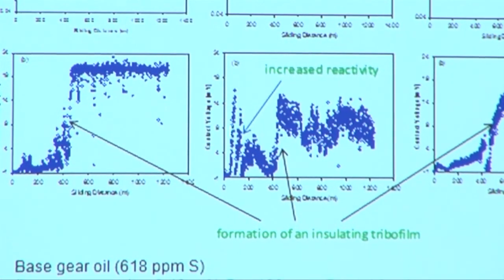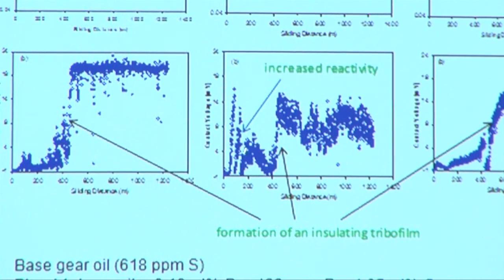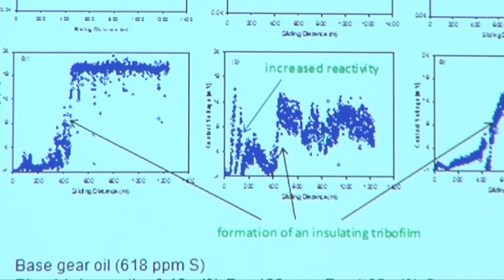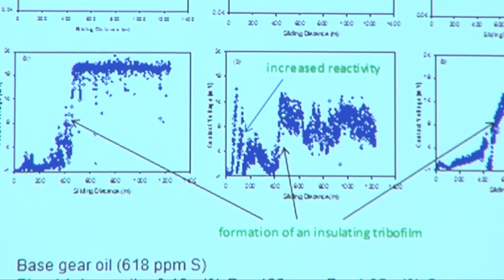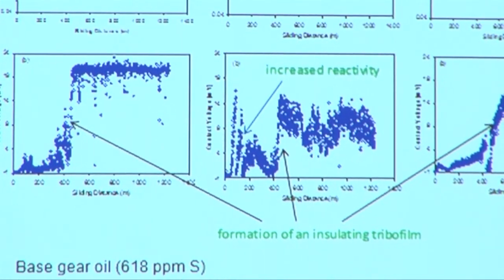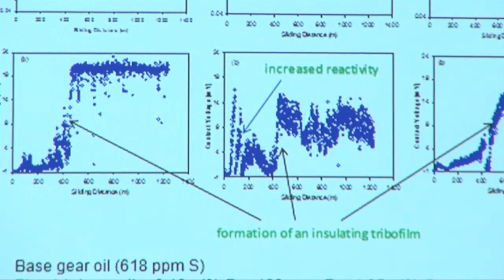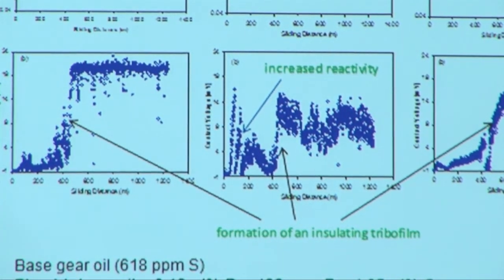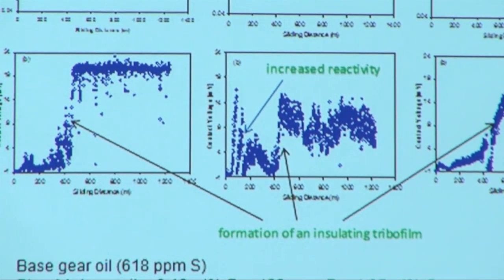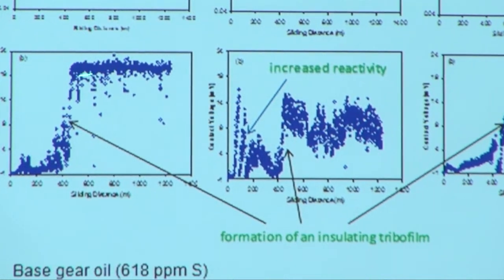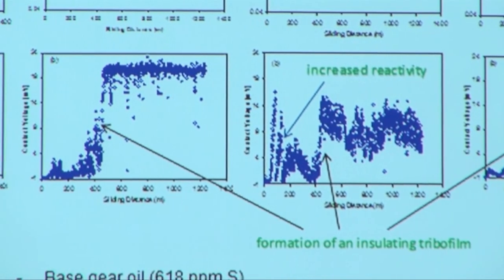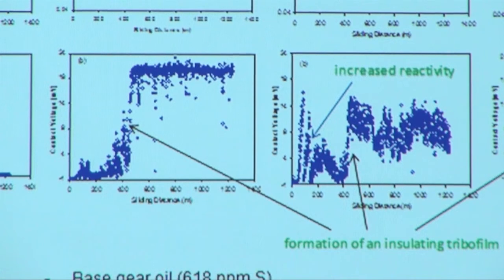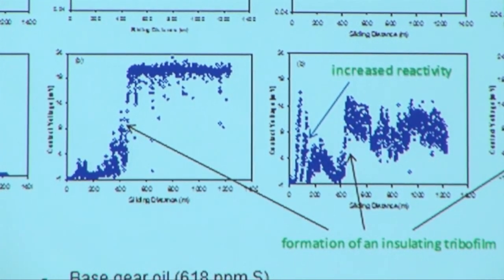We can see these sharp spikes and fluctuations of the contact voltage that is no longer zero, reaching a steady state that is more fluctuating than this, but overall producing better wear characteristics. These fluctuations may indicate that it's rapidly removed and is reforming, as opposed to this one being mostly formed and very slowly removed, but this one may have better wear characteristics and friction characteristics because of its different composition.